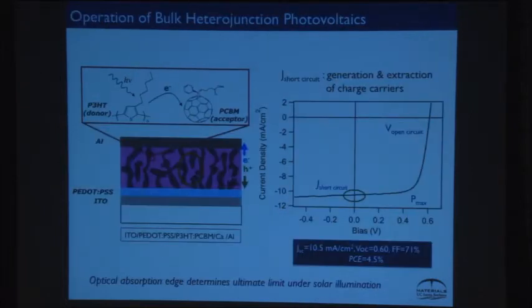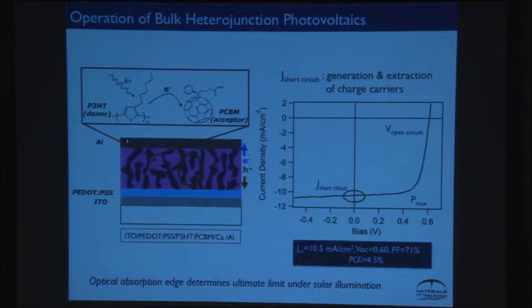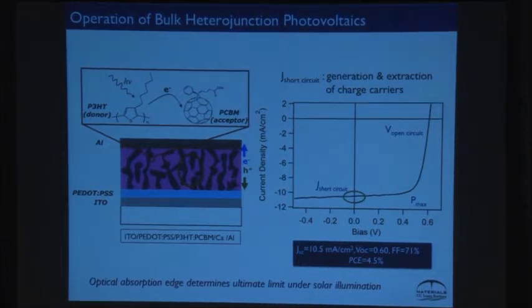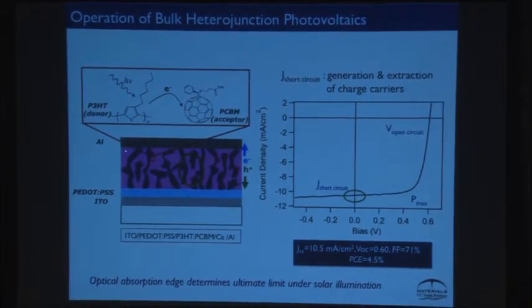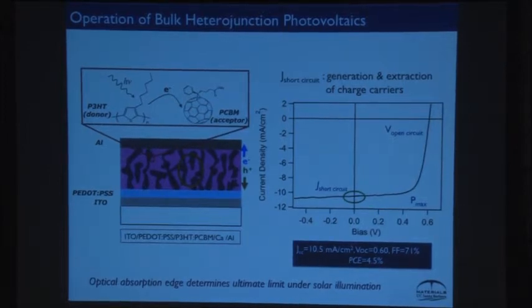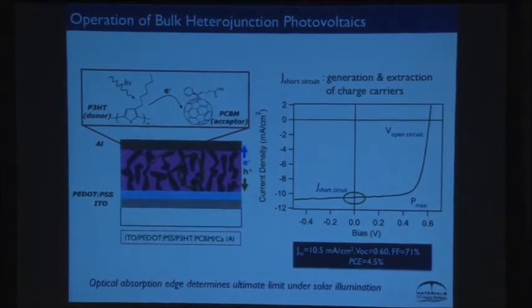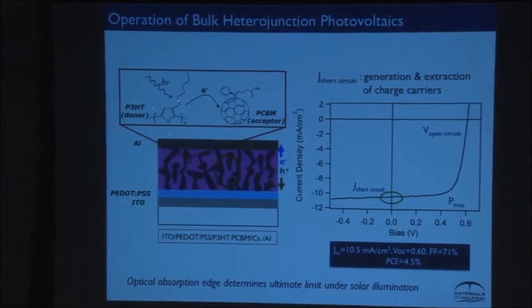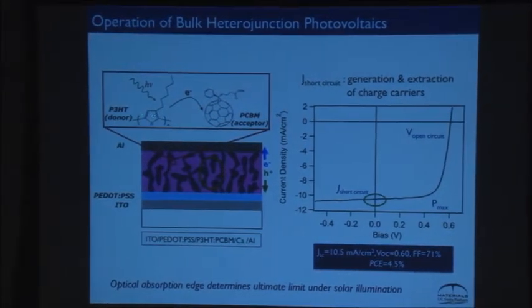But what's actually happening in these cells? Let's look at a solar cell curve if you're not used to looking at that. What I'm going to do is make a mixture of these two things in solution, maybe a 1-to-1 by mass blend. I coat them with a solvent and let the film dry. And we get a phase separation in these layers such that it's quite small. You have nanoscale, maybe 10 to 20 nanometer domains of both of these things in an efficient cell. The reason you need that is because the optical excitation in this material just doesn't move very far.